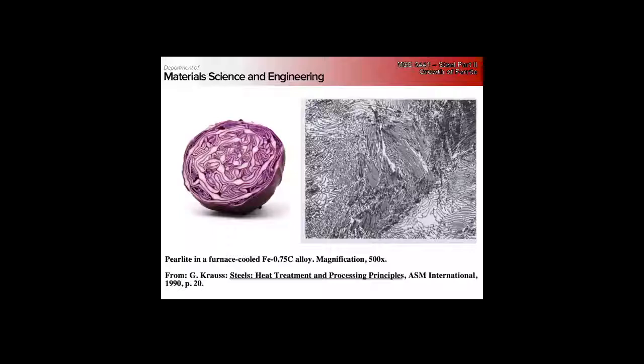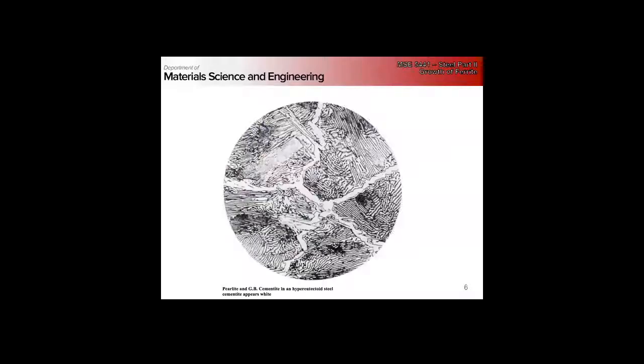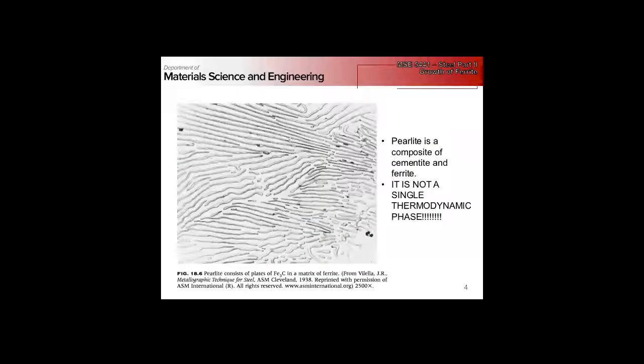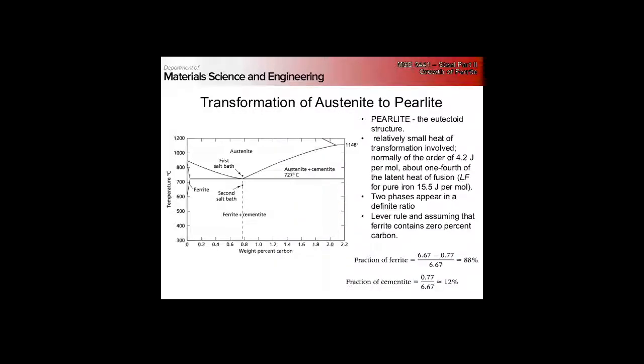And just here's sort of an example. Here's what it looks like when you're hypereutectoid, right? Our grain boundary cementite with pearlite in between, and then if we're at the eutectoid structure, right, and we come down, we can just use the lever rule to determine what the fraction of the ferrite versus the fraction of the cementite is, right, given our carbon content.